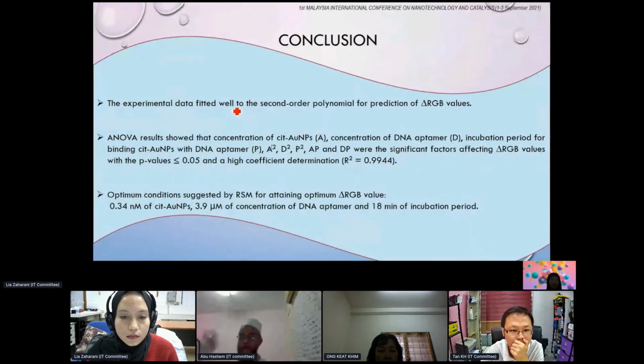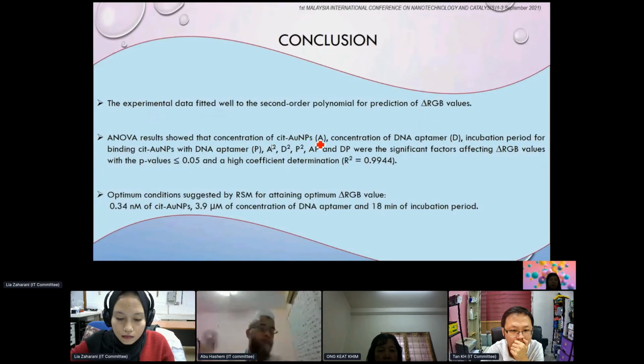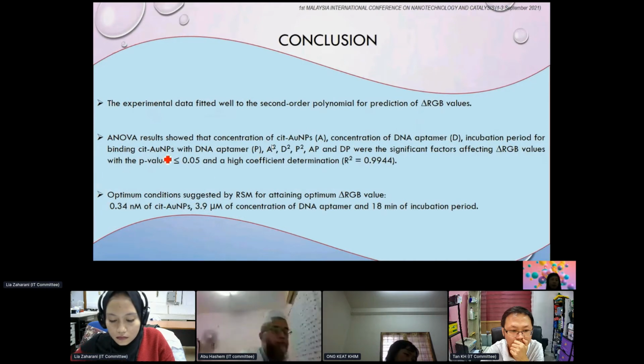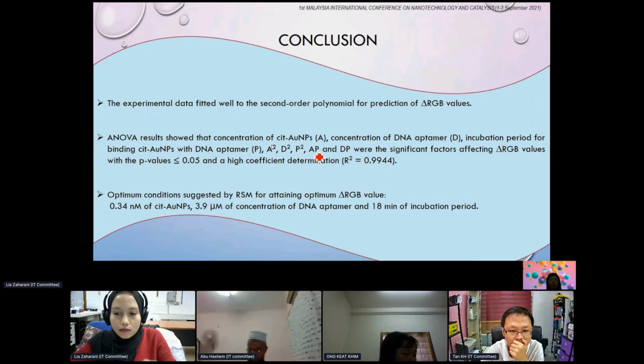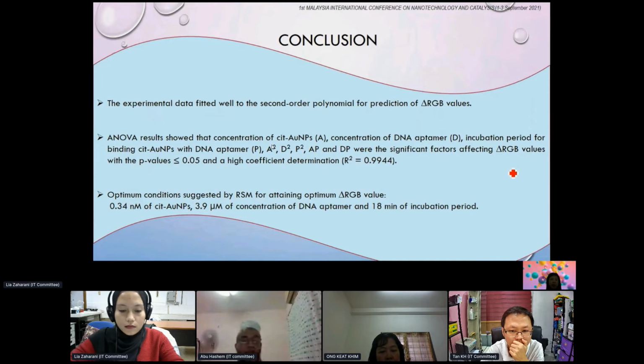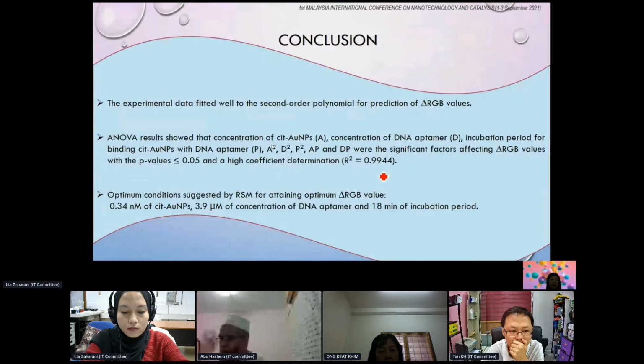The experimental data fitted well to the second order polynomial for prediction of delta RGB value. ANOVA results show that concentration of cit-AuNPs, concentration of DNA aptamer, incubation period for binding cit-AuNPs with DNA aptamer, interaction effects A power 2, D power 2, P power 2, and interaction effects between AP and DP were the significant factors affecting the delta RGB, as indicated by p-value less than 0.05 and a high coefficient of determination R square, which is equal to 0.994.